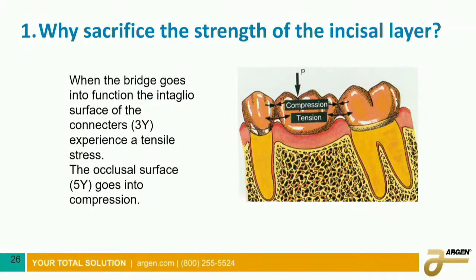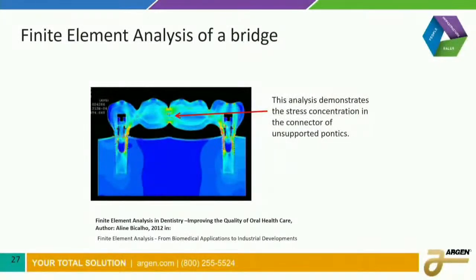Now, the first thing when you look at it, you say, well, okay, we could put a weaker material on the surface, on the incisal layer, because, for example, when we have a bridge and that bridge goes into function, the occlusal layer is going to be in compression, but the intaglio surface is going to be in tension. So if I have a 3Y, a stronger material down here than I have on top, I'll be okay. And that sounds reasonable, and sure enough, when you do the computer studies, you find that's exactly what happens.